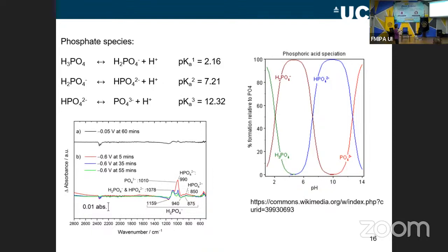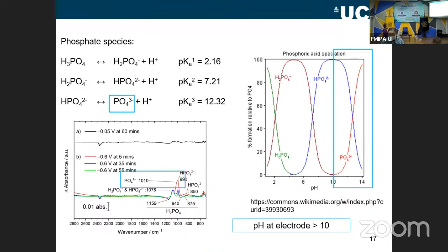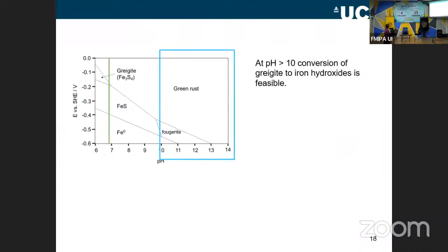So what's happening is we think that the spectrum is showing that when I apply the potential, I now have a signal in the infrared for PO4 3- that wasn't there before, and it wasn't there in the starting solution. So the starting solution only had these species. So if I have PO4 3- in my solution, it means I'm in this region here, which tells me that the pH near the electrode has to be greater than 10 in this situation. And as I showed before from this diagram, at pH greater than 10, I can turn my greigite into iron hydroxide. So that's what we think is happening.